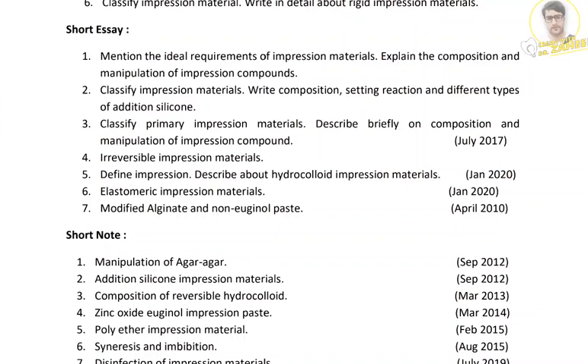We have to write regarding the ideal requirements. They should be fluid enough to adapt to the oral tissues, and viscous enough to be contained in the tray seated in the mouth. While in the mouth, they should transform into a rubbery or rigid solid in a reasonable amount of time. Ideally, the total setting time should be less than seven minutes.